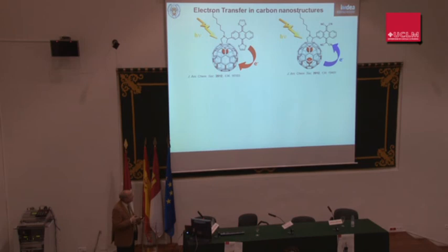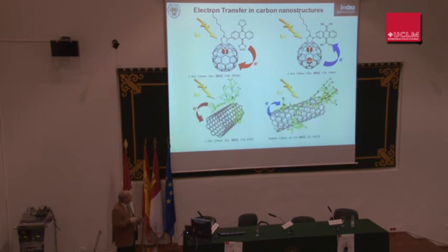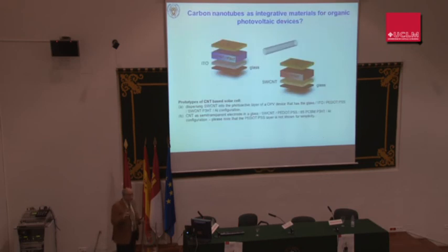And we have carried out basically the same involving carbon nanotubes. This is another paper reported very recently, mostly involving these molecular tweezers, which are soluble in water media, and electron transfer. So here the carbon nanotube acts as an acceptor, but also as a donor. I have only 2 slides for finishing. One is this one: what about carbon nanotubes? Carbon nanotubes are a pain in the neck. They are really difficult to use for these purposes.